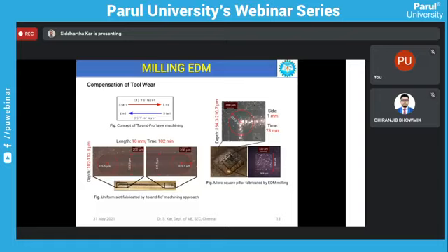So basically we can see that the slot that has been machined is not at all uniform. There is variation of depth in the four corners, but the square pillar is uniform. As we can see, a 269 micrometer square pillar has been achieved. So this suggests that in order to fabricate three-dimensional cavities by micro-EDM milling, we have to optimize the tool path movement. So if we can optimize the tool path movement, then only we can achieve lower variation in depth.